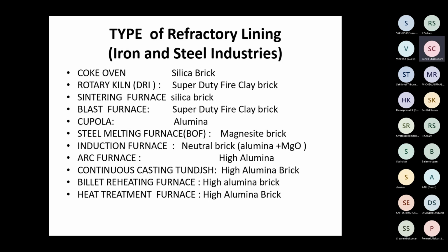These are being used where the coke oven, the silica bricks, rotary kiln, super duty fire clay bricks, rotary kilns in the DRI or sponge iron. You find plenty of them if you go to the Odisha belt, Jharkhand, even the Raipur area. You will find quite a number of rotary kilns where you make sponge iron. Sponge iron is the main ingredient for your steel plant. Many steel plants don't have sponge iron, and you can't run a mini steel plant without it. But an integrated steel plant doesn't need any sponge iron.